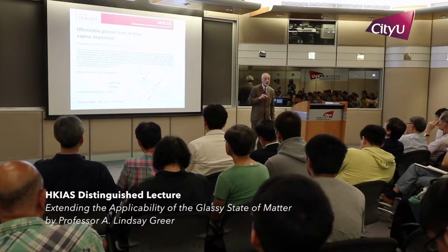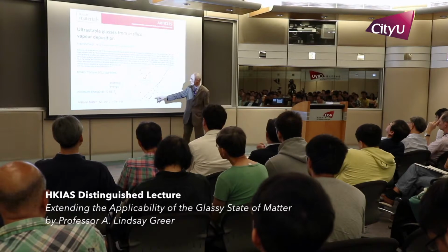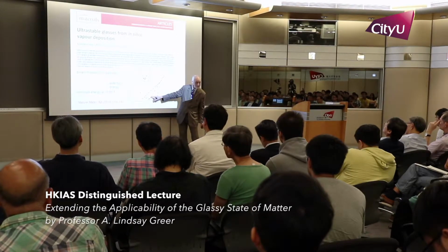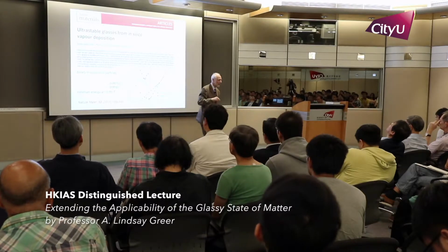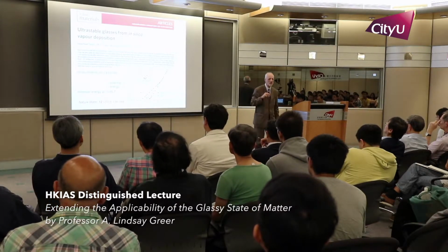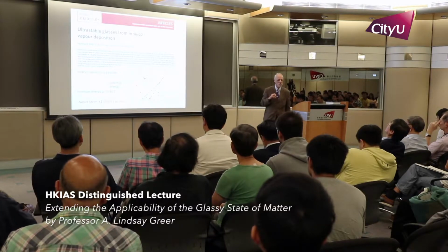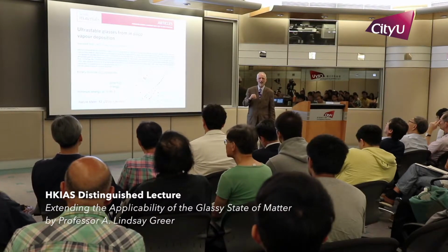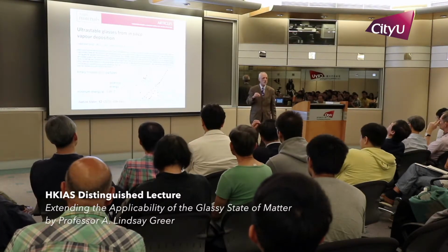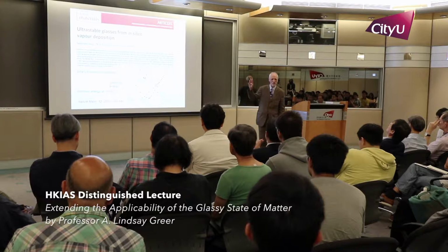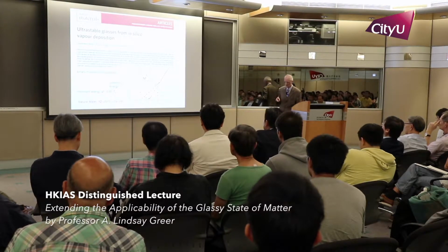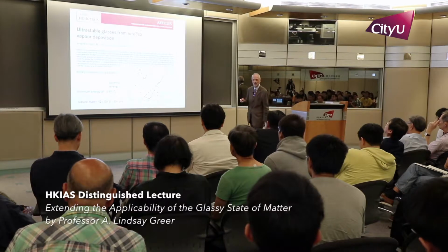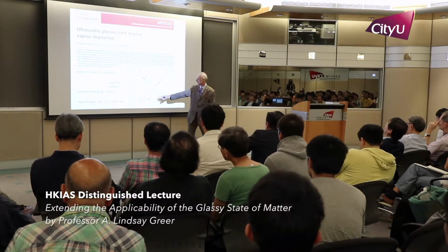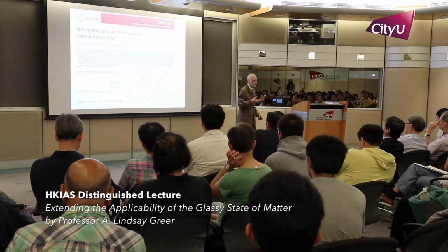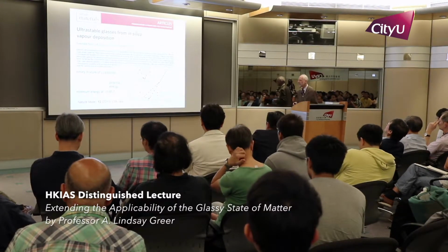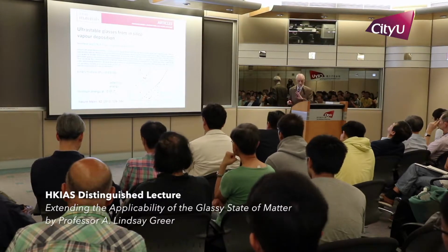It's quite easy to extrapolate how slowly you would have to cool to reach that if you were cooling the liquid, assuming it didn't crystallize. And the answer, incredibly, is as slowly as 10 to the minus 14 Kelvin per second. That, if you were to do it, would take you 1/10 of the age of the universe to get from the melting temperature down to Tg. Or equivalently, if you were to take a standard glass and anneal it for long enough to get to that energy, it would take you again about 1/10 of the age of the universe, roughly 1.6 billion years to get there at the maximum. That's the extreme case.